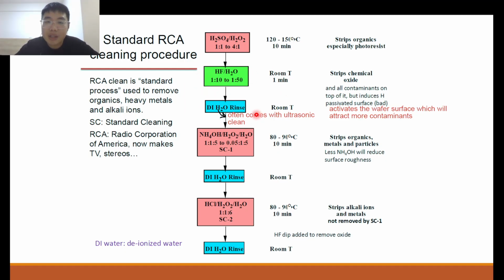So after that, you can do a DI water rinse. Then after that, we can do your SC1. Remember, your basic solution first. Then a rinse. Of course, you have to rinse it first before changing to acidic solution. Acidic solution is your SC2. And then finally rinsing, and then you have to spin dry the wafer for the next step, because oftentimes moisture is not good for many steps.